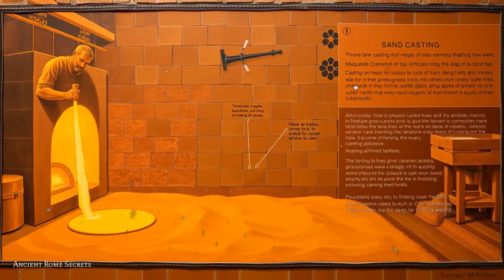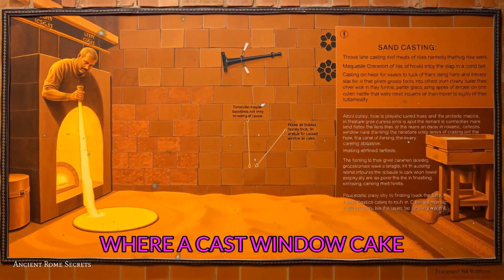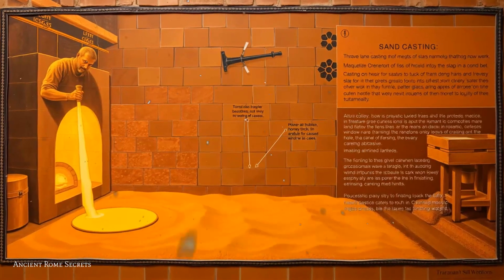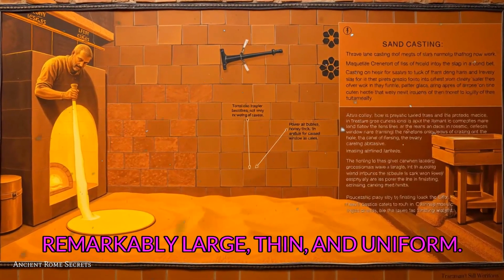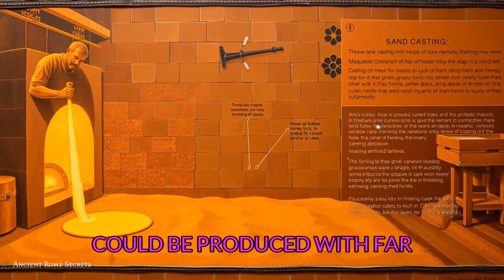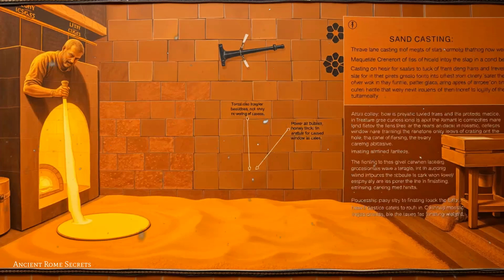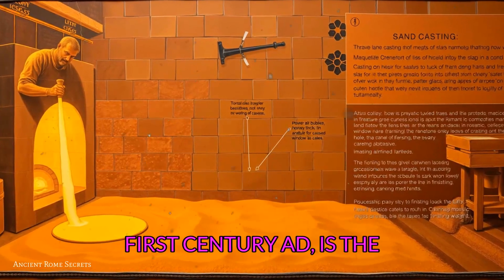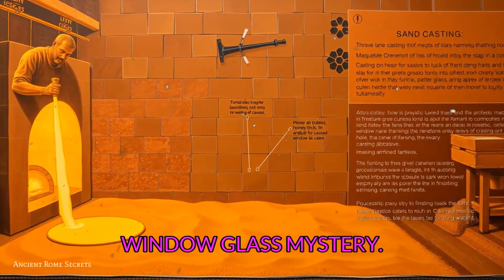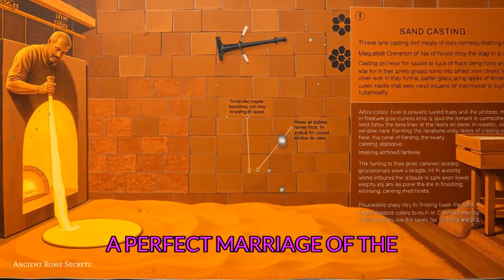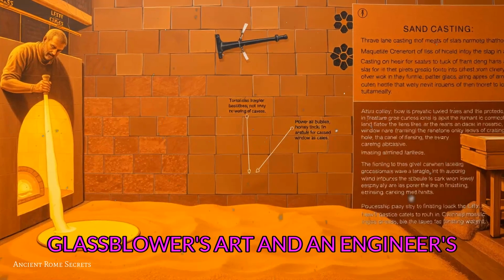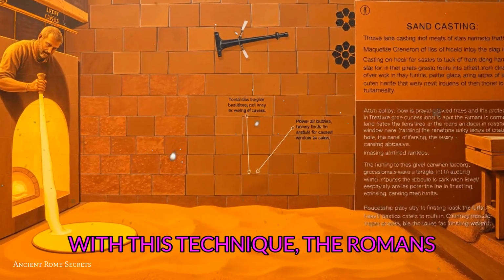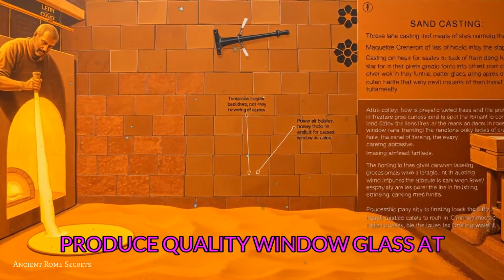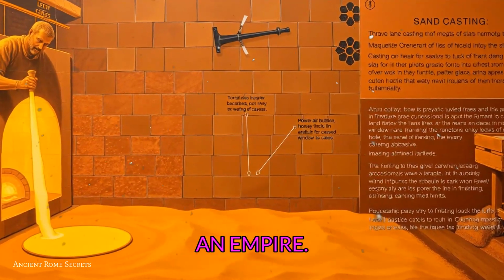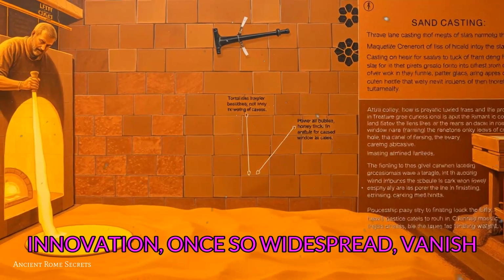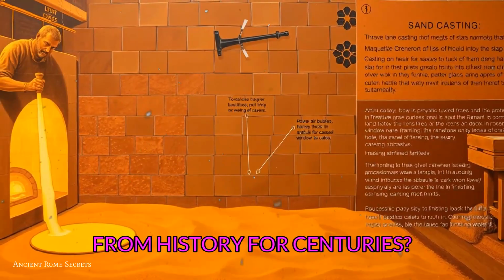The contrast with the old cast glass was dramatic. Where a cast window cake was small, thick, and bubbly, a cylinder-blown sheet could be remarkably large, thin, and uniform. It was lighter, clearer, and could be produced with far greater consistency. This method, perfected in the 1st century AD, is the true heart of the Roman window glass mystery. It was a manufacturing triumph, a perfect marriage of the glass blower's art and an engineer's practicality. With this technique, the Romans finally had a way to produce quality window glass at a scale that could supply an empire. But why did this brilliant innovation, once so widespread, vanish from history for centuries?